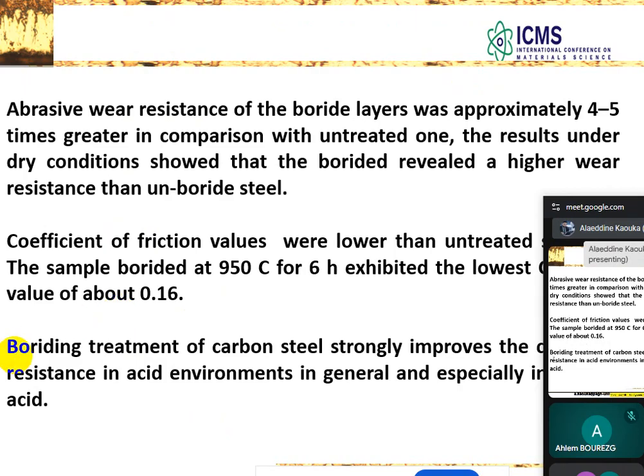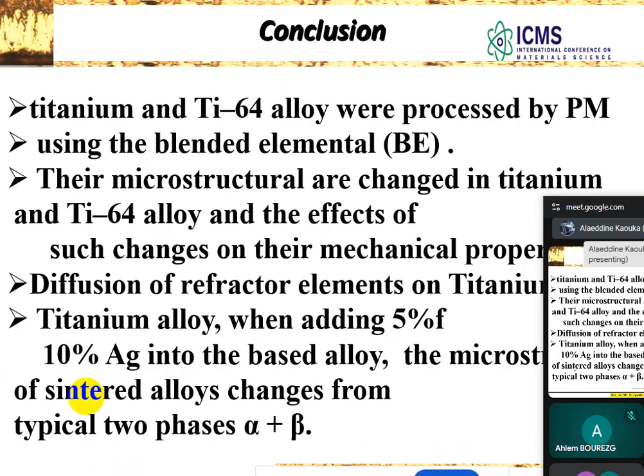So the abrasive wear resistance of boride layers was approximately 4 to 5 times greater in comparison with the untreated one. The results under dry conditions revealed a higher wear resistance than the untreated steel, and the coefficient of friction values were lower than the untreated, about 0.16. So finally, we can say that we achieved this, and the titanium alloy treated was processed by powder metallurgy using blended elemental powders.